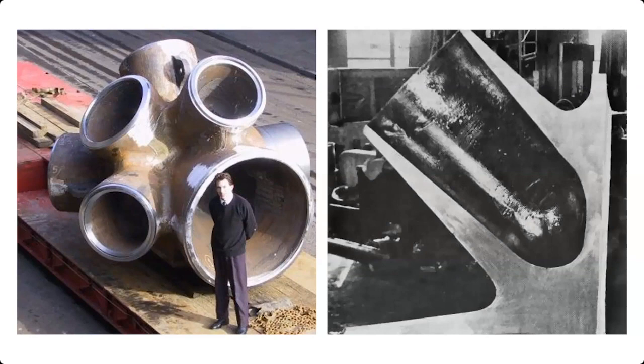Non-destructive examination techniques had advanced, as had finite element analysis techniques. And so in the cross section there, you can see a good example of how the high connection forces, which are happening at the center of that joint, are being addressed by more material. Whereas away from those high connection forces, we can thin out to match the member wall thickness. Again, concentrating the material where we need it, and vastly simplifying fabrication. You can see there's no weld toe overlap that's going to happen at this location. And because we're moving the welds away from locations of high stress, there's again an improvement in fatigue performance.